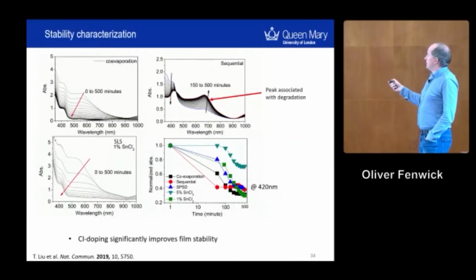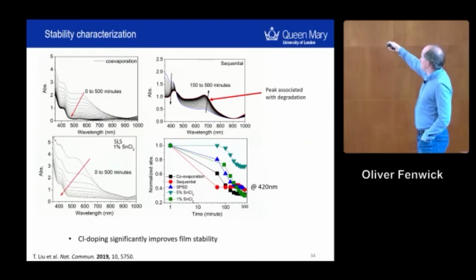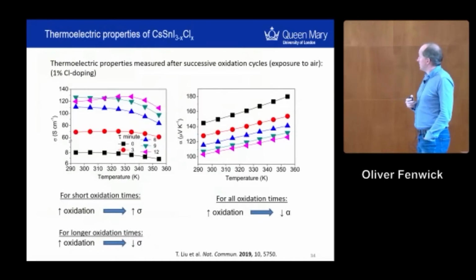Does it affect the stability? Yes. So the key plot is the bottom right-hand side here. We're just following the absorption at a particular wavelength, and we see that this one up here, which is the 5% tin chloride doped case, is significantly more stable in air than the others, optically.